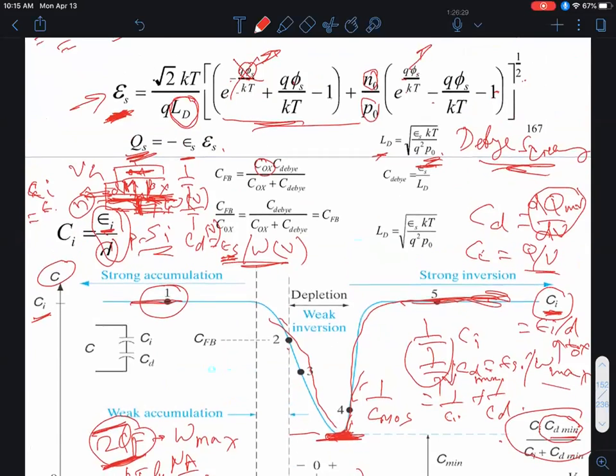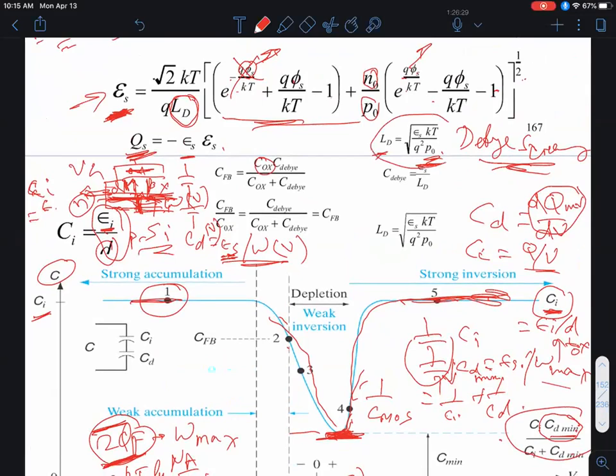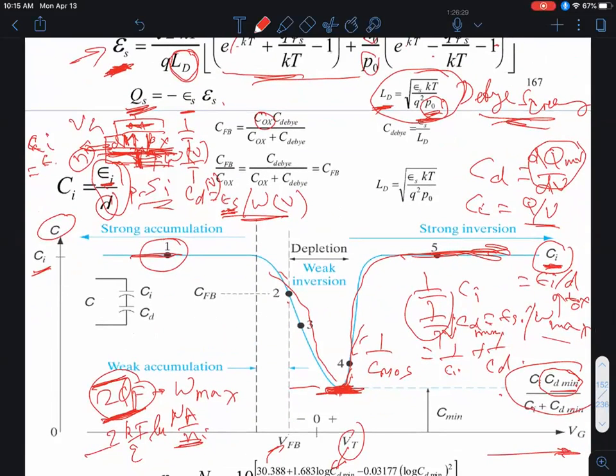Once I get the doping concentration, we talked about this quantity called the Debye screening length, which depends on the carrier concentration. So once I extract the carrier concentration, I can get the Debye screening length, which turns out to be very important because, and I'm not going to prove this, under flat band conditions, the flat band capacitance is found to depend on the series combination of the oxide capacitance and this Debye capacitance, which is epsilon semiconductor over the Debye screening length. It's not that hard, but we don't have time for that.